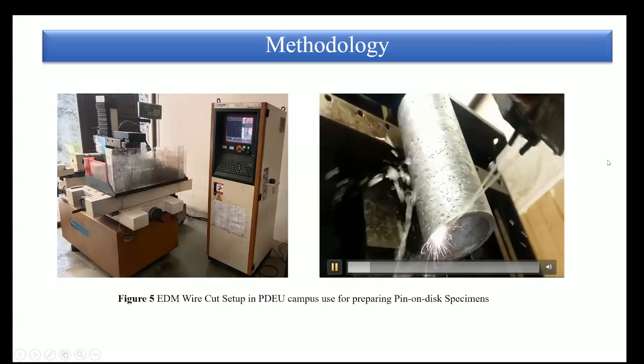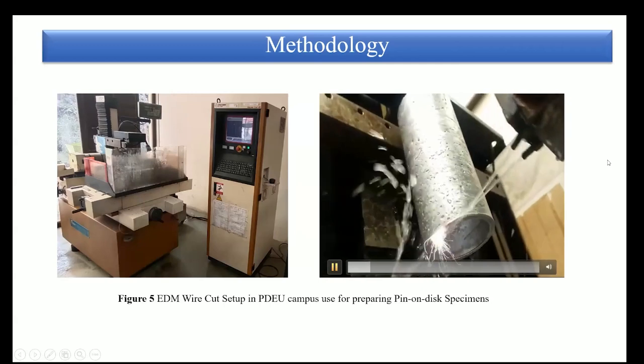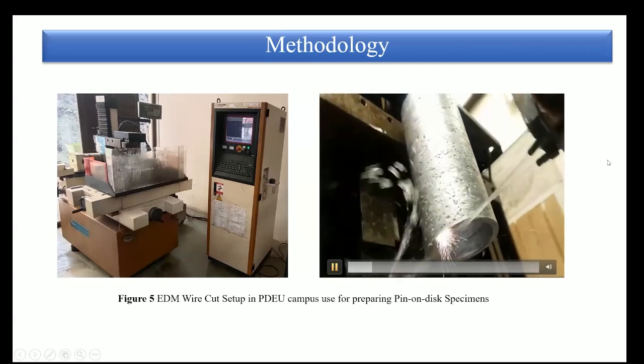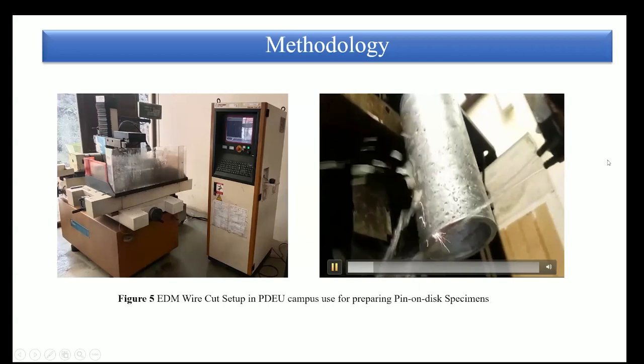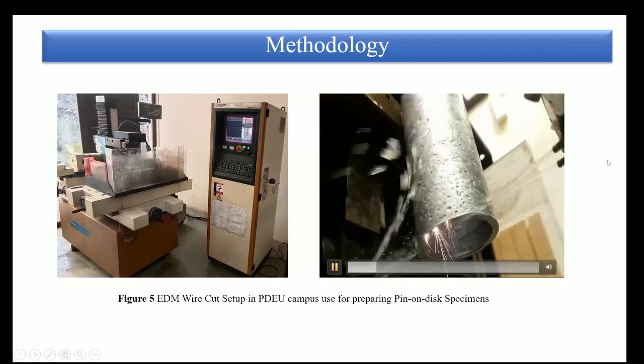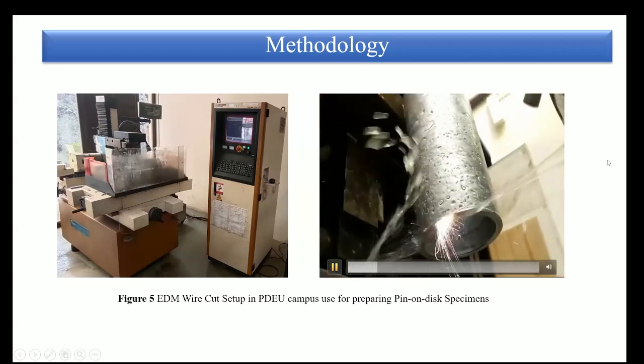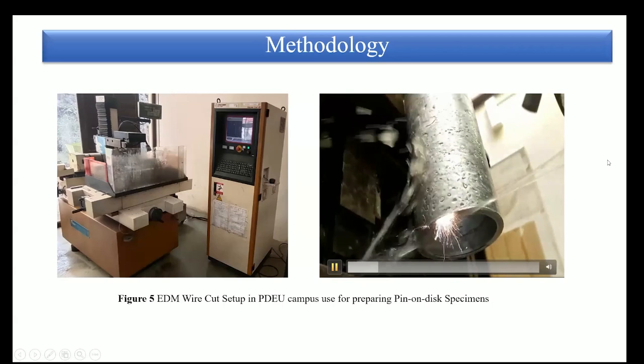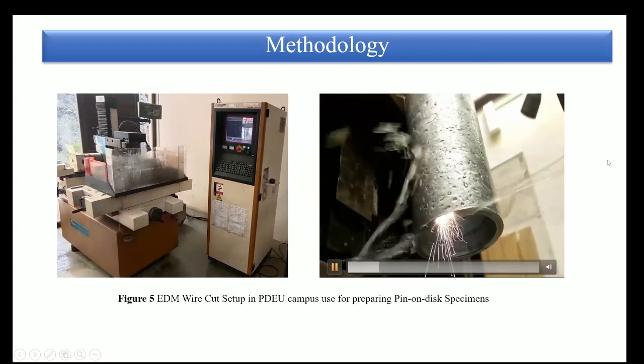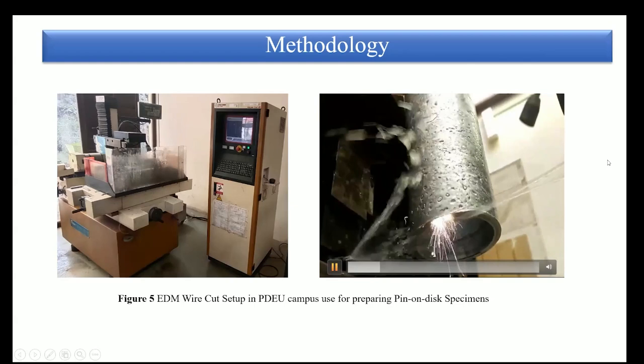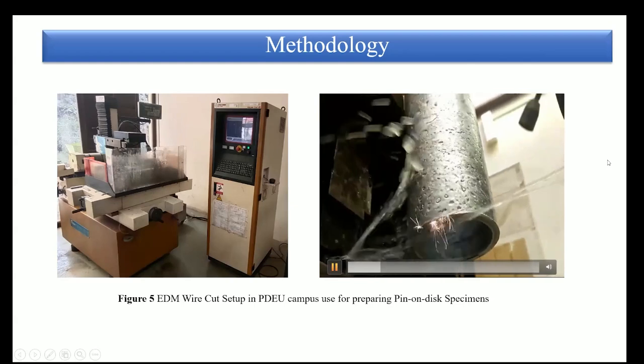Specimen for density and porosity, and Keller's reagent. For the etching, we prepare Keller's reagent with 190 ml distilled water, 5 ml nitric acid, 3 ml hydrochloric acid, and 2 ml hydrofluoric acid. It is used for making the Keller's reagent. With the reagent, we check the microstructures.